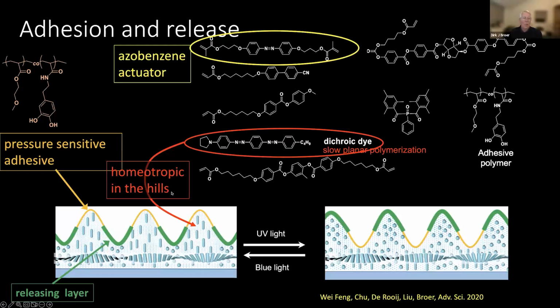So by doing this, we indeed have the perpendicular orientation at the hill and the planar orientation at the bottom. Now we add another component, and that is a pressure-sensitive adhesive. We are using this protein type of molecules, actually inspired by the muscle proteins that mussels use to make them adhere to the rocks in the ocean. And we took care that this protein is at the top, just by dipping in the state where the tops are present in the thin film of this adhesive.